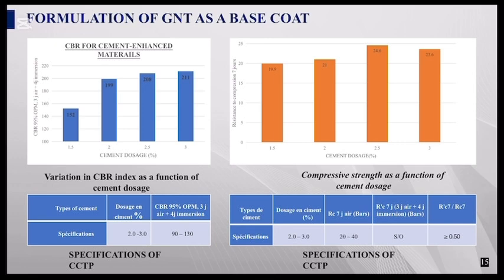more than 130. The choice of this dosage is justified by the fact that the other mechanical characteristics of the material give it flexible character, while the dosages of 1.5% and 2.0% cement, leading respectively to 7 days compressive strengths of 19.9 and 21 bar, are barely equal to or higher than the required minimum strength of 20 bar, which could lead to lower mechanical performance when the hazards of on-site application are taken into account. Adjustment of spreader metering devices.